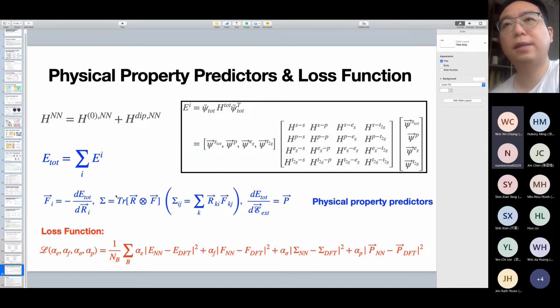Okay, so the idea is that you use the machine learning to fit the energy close to the energy obtained from DFT, then output this force or energy information to the MD simulation. And after the MD simulation, you can find the delta E. If the delta E is bigger than some threshold, then you will add a new sample, put it into the data set, and then redo that again. That's right. Okay, I see.